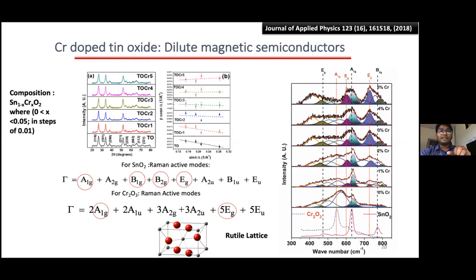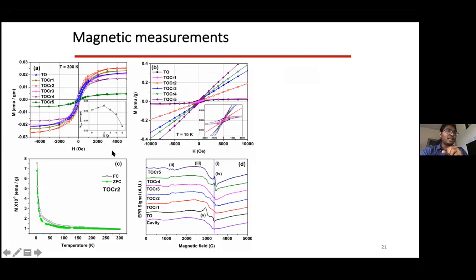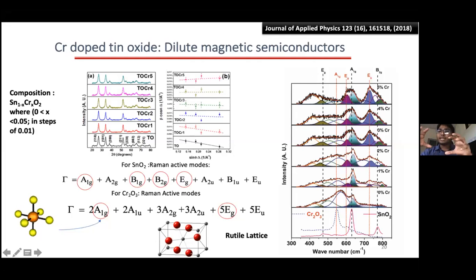So it so happened that when you dope it with chromium, you are actually putting this chromium at the tin site. Chromium is essentially trivalent and tin is tetravalent. You are creating somewhat of a charge imbalance. Just to accommodate that charge imbalance, there would be one oxygen vacancy associated with each of this doping. And how would you confirm that?